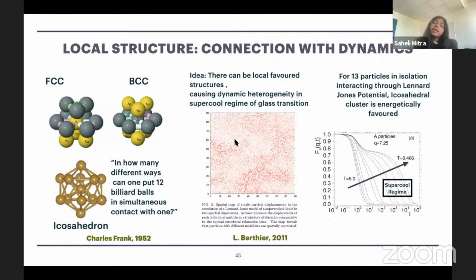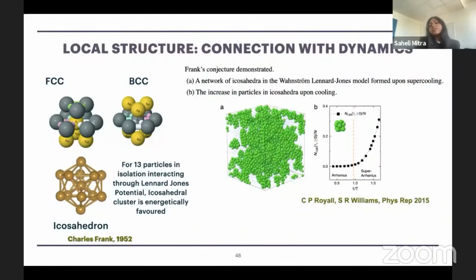And then the idea came that maybe in the supercooled regime, when the system has become dynamically heterogeneous, it can be related to local favored structures. There have been many studies in this regard. I am presenting only one example, from the group of Paddy Royall, where they find that indeed in the supercooled regime, for their system, the association to icosahedral clustering increases at low temperatures.